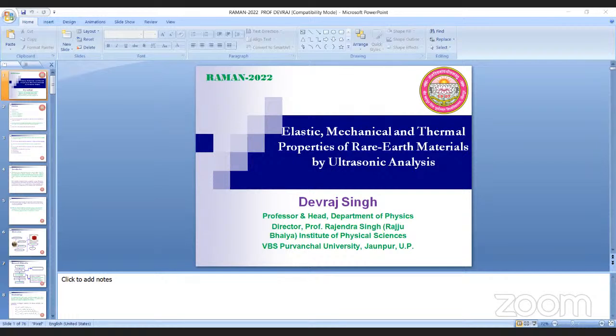And for thermal conductivity, using these elastic constants, density, and these parameters, we compute the Debye temperature, pressure derivative of elastic constants, acoustic coupling constant, thermal conductivity, and Gruneisen parameters. Next, please.